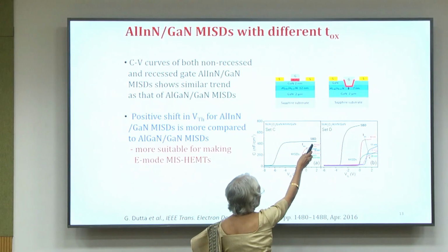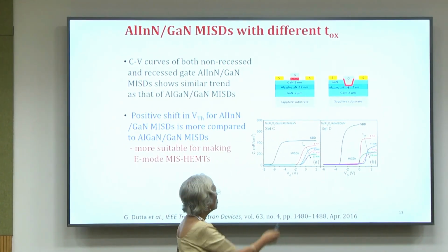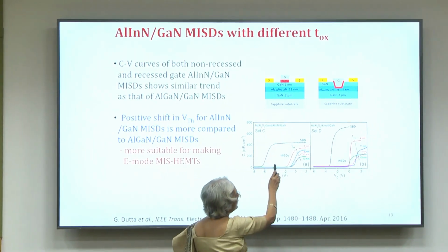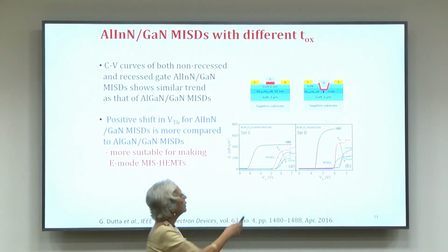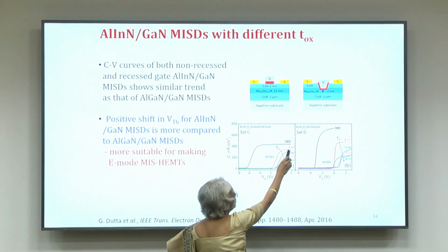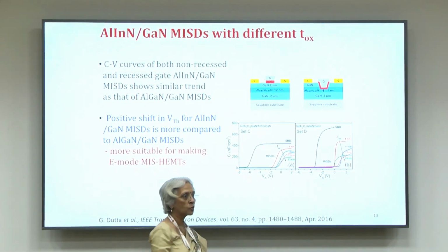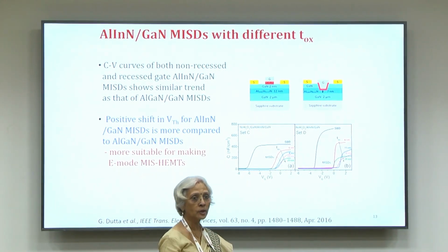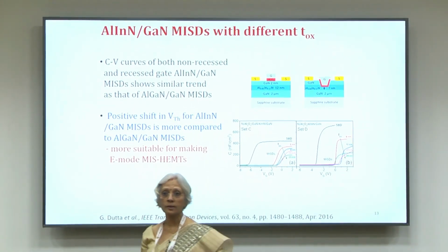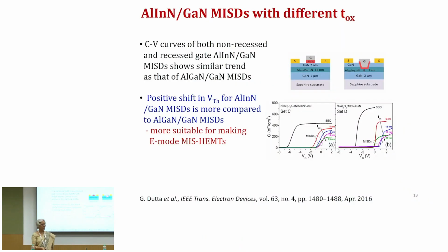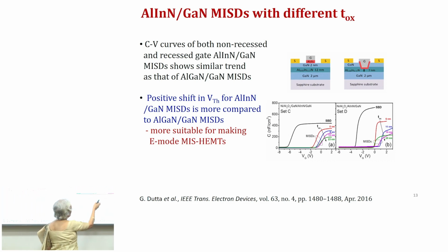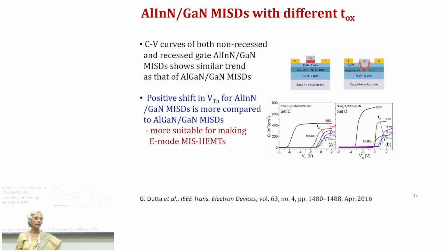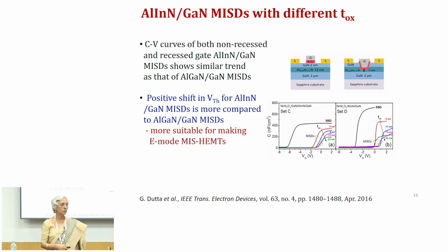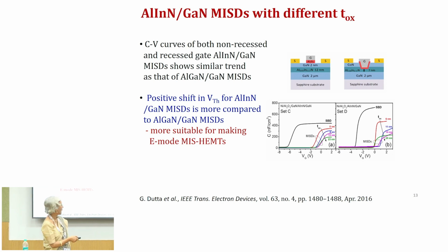As you can see here, this is the CV characteristics of the Schottky barrier diode showing a large negative threshold voltage, and then as we keep on increasing the gate oxide thickness, you can see 5 nanometer to 8 nanometer to 13 nanometer, the threshold voltage is actually shifting more and more towards the positive direction. So, as I said, our hypothesis was that thicker gate oxide will make the positive shift more and more, was partly justified, because eventually when you go to a much thicker gate oxide, 23 nanometer thick oxide, we found that the threshold voltage is again starting to go back. We have a reason for that also, I will come to that later.